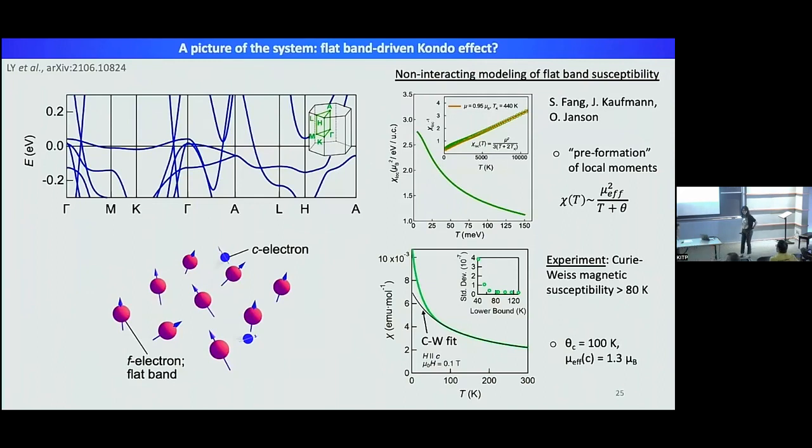I would think that the heavy fermion mass increase can typically look like that even in an antiferromagnet, because you get a very large constant. If you plot it on log scale, you can of course deviate to the positive in a heavy fermion antiferromagnet, because you have a very strong Pauli susceptibility, and then it will level out at low temperature. Right? You start Curie-Weiss at high temperature, and you deviate to the positive to go to large Pauli. You don't think so? I think it's standard.